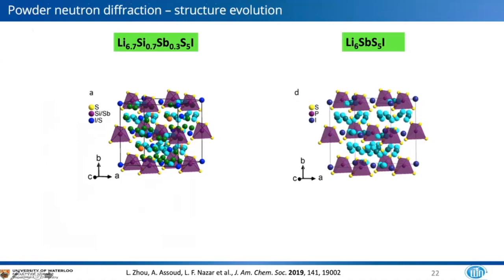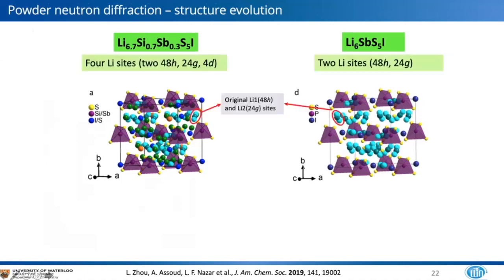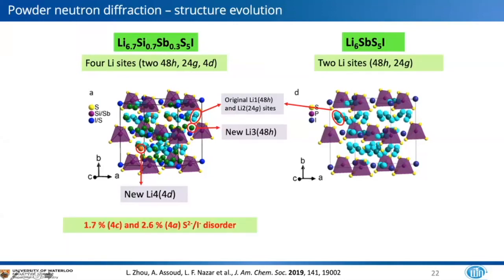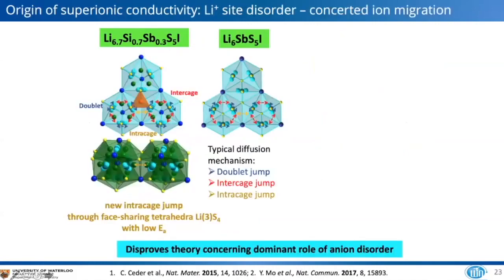So comparing the structures of the pristine argyrodite with our silicon and lithium substituted material, we see that we have 4 sites in the case of this new silicon substituted material, where only 2 sites in the pristine material, and these are indicated by these arrows. And again, this is achieved with very little anion disorder.